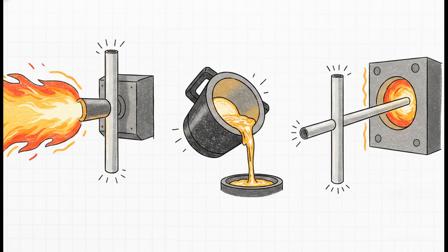You're going to find silicon nitride totally dominating in induction heating fixtures, burner nozzles, thermocouple protection tubes, and molten metal handling. Why? Because it provides that essential thermal isolation and almost entirely prevents thermal cracking in systems that undergo brutal rapid thermal cycling. Where other standard materials just crack and degrade, silicon nitride stays completely stable.